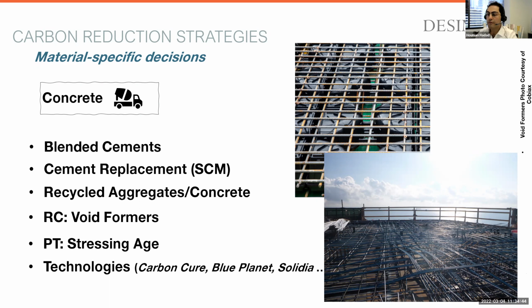So if you are shooting for 3,000 PSI in 12 hours or 24 hours, which is very common when you're pouring PT slabs, it is challenging to replace 50% of cement with fly ash. It's doable, but then instead of having a 6,000 PSI concrete, you probably have to specify 8,000 or 9,000 PSI concrete to gain an early strength that works for you. So it's offsetting a little bit of that reduction that you have been making in cement replacement.